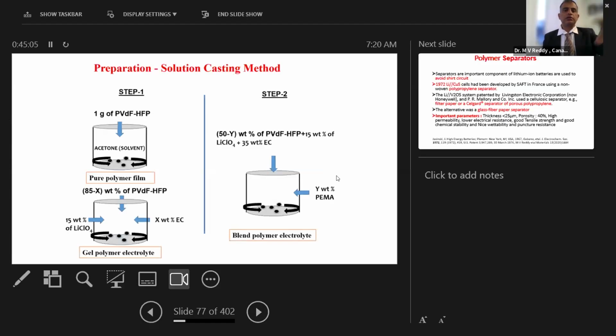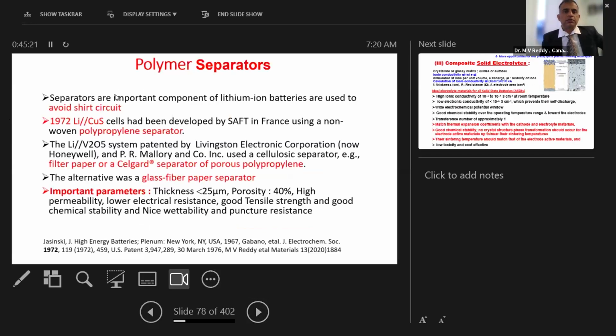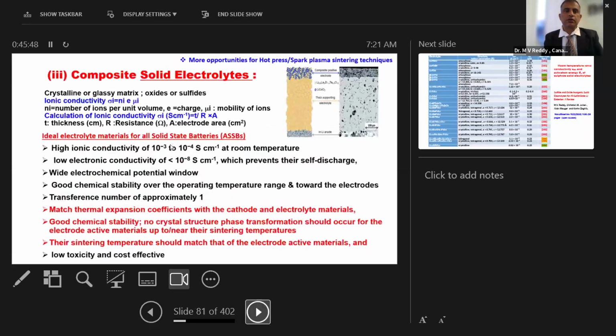Again, either in a laboratory at a small scale or bigger, you can finally put it in a petri dish and dry it, and you can do that if it is a lithium-based system. A glove box is good, in order to avoid further reaction of the lithium salt with the air. Polymer separators, which I already mentioned, prevent short circuits. Thickness should be less than 25 micrometers. Porosity, good permeability, and good tensile strength are really very important, because sometimes the separators get punctured, and wettability is also very good. So these characteristics of the separators are very important.